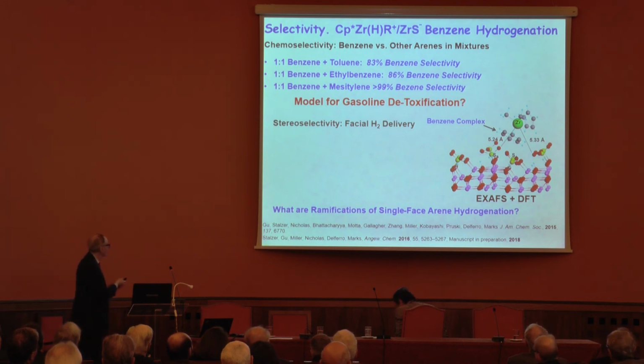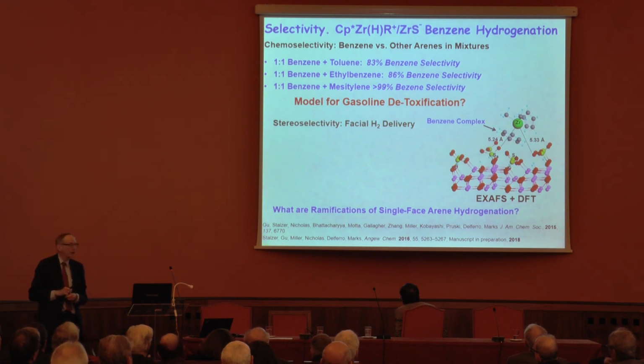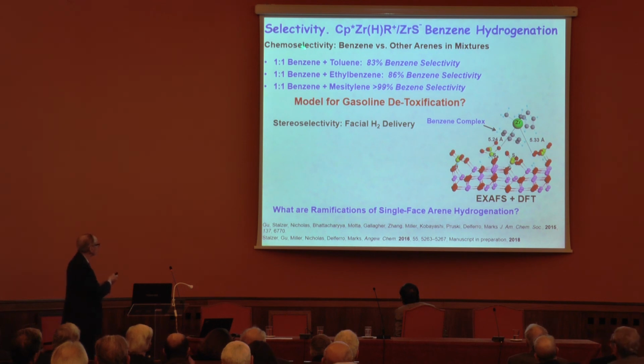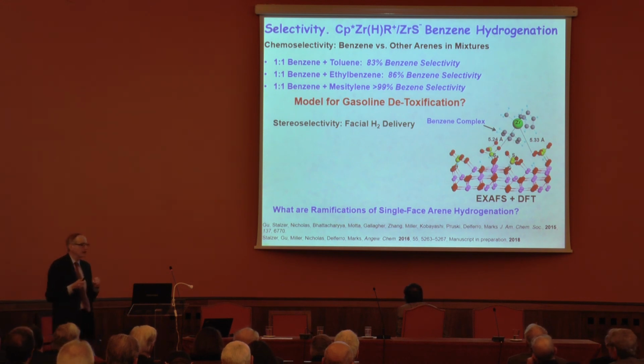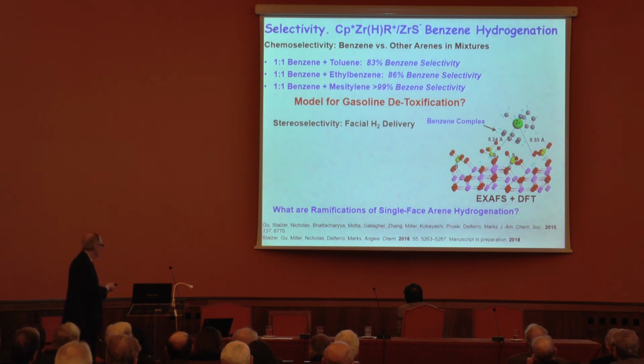But the interesting thing in terms of what it's good for is when we feed this catalyst mixtures of benzene and toluene, benzene and ethylbenzene, all these other aromatics, which in fact is what is in the gas tank of your car. Your car has about 1/3 aromatics as the fuel. And benzene now is a recognized carcinogen. That has to come out. We need the rest of the aromatics for octane, for performance, for energy efficiency. How do you get the benzene out? It turns out to be a non-trivial problem. This catalyst has a very high selectivity because of the constraining groups around the active center, a very high selectivity for hydrogenating benzene. So it's a model for detoxifying gasoline. We think it's got a lot of prospects.